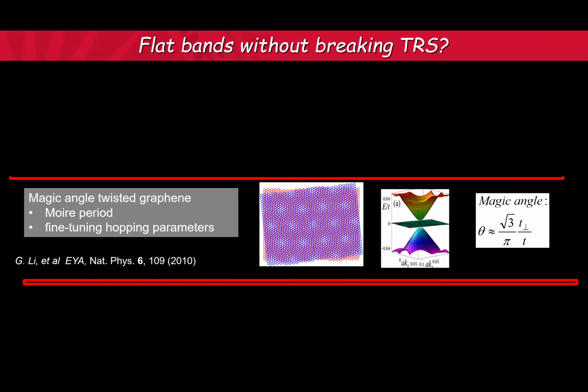One way is the well-known magic angle twisted bilayer graphene. It turns out that there's a sort of resonance effect when the twist angle, you see, the twist angle is the ratio of the interlayer to intralayer tunneling. And there's a special angle where you get a resonance that gives you a flat band. This flat band can be mapped exactly onto pseudo-Landau levels, as I will show.